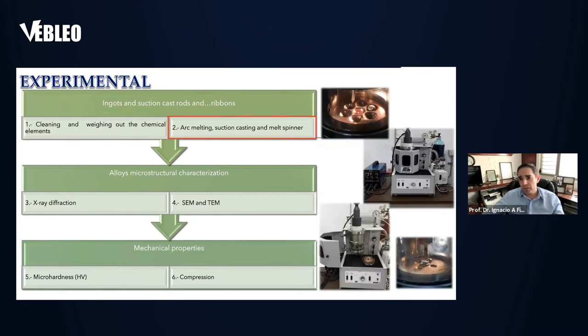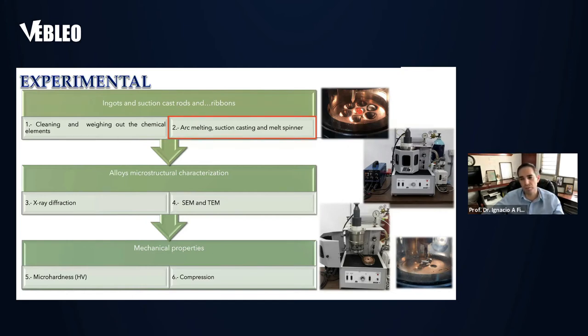We use an arc melter. This is the arc melter here. We use the titanium ingot because we operate under vacuum and then fill with argon, and we melt the titanium first as a getter — basically there is oxygen remaining, and it goes into solution with the titanium. This is our sample, here the copper plate and the titanium electrode. I have three arc melters: this is the smallest one, where you can produce 10–15 grams of sample. The other is 50 grams and the biggest is about 200 grams of sample — for research, more than enough.